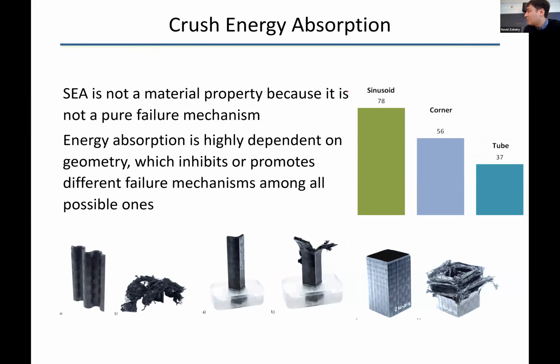But then people started doing a lot of tests, and many of these tests were done at the University of Utah. Professor Dan Adams did a lot of tests in that university with different shapes of these tubes. And it's not just the shape. Actually, when you do the test, it becomes how you do the tests. What are the boundary conditions? And people also realized that if they have flat top surfaces, or tapered edges like that, it would have a huge impact. I don't know if you can see it, but it's tapered at the edge. It might become difficult to measure if you don't have these tapered ends.